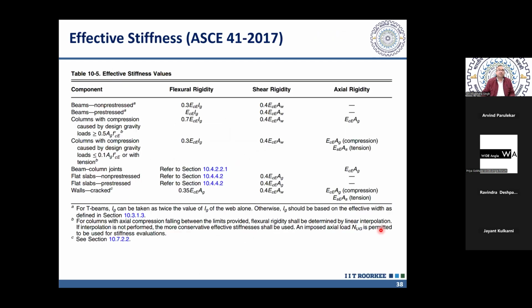And what ASCE 41 gives us, first the cracked section stiffness of different members. So in case of beams, it is 0.3 times the gross stiffness, E_c into I_g. And here you see E_CE. So this E stands for expected strength. And expected strength is f_ck plus 1.64 sigma. So you remember how we obtained the characteristic strength? The characteristic strength is obtained by mean strength minus 1.64 sigma. So expected strength, which is the mean strength, is characteristic strength plus 1.64 sigma. So in case of nonlinear analysis, we will be using expected strength, not the characteristic strength, because here we are not using any factor of safety on strength.